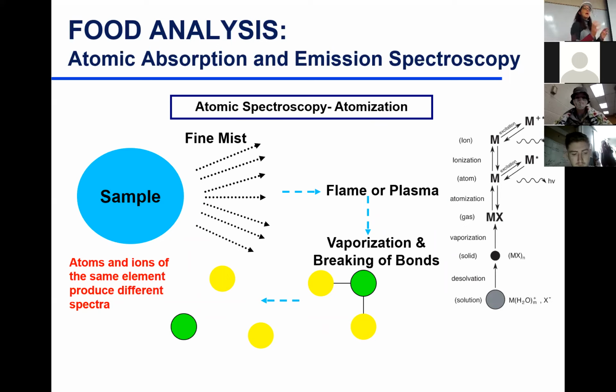So if the flame is not at the right temperature, if let's say it's too cold, relatively cold, I mean not necessarily hot enough to break the molecules, you might have molecules not broken that might scatter your light. Then less light will reach the detector, and the detector will give you higher absorption, because the detector will assume that less light is coming to it. That means more was absorbed by the sample. But it's false, because the flame was not hot enough. Your molecule did not break. It was there in the flame. And when the light is coming, it's getting scattered by the molecules, and less light is reaching the detector.